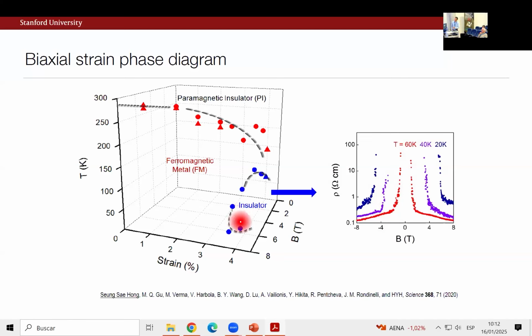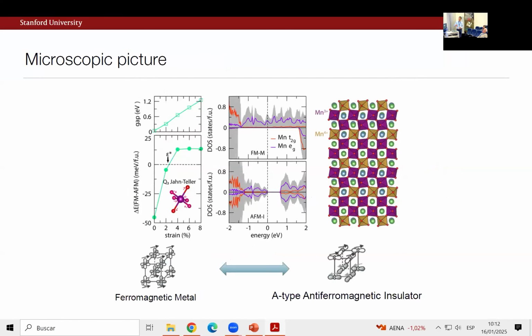This is actually relatively fragile to melting under magnetic field. So this is, for us, unmeasurably high insulator, but just by putting on a few Tesla magnetic field, you can suppress this insulator, okay? So again, that phenomenology is not dissimilar to what you see in other manganite systems.